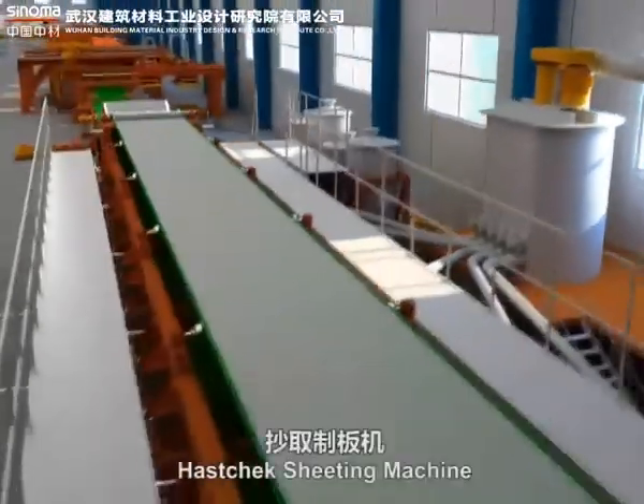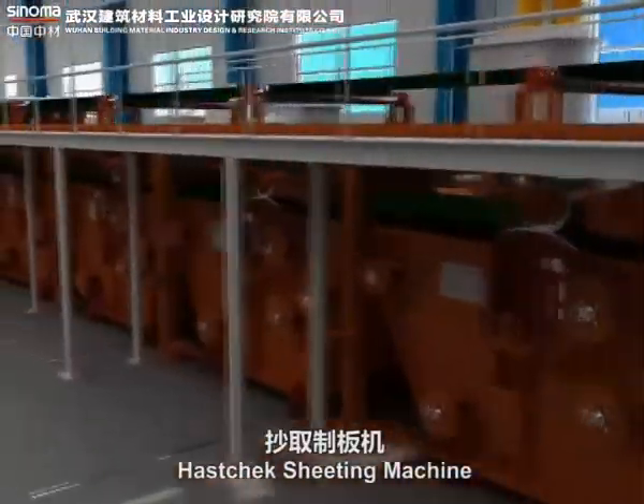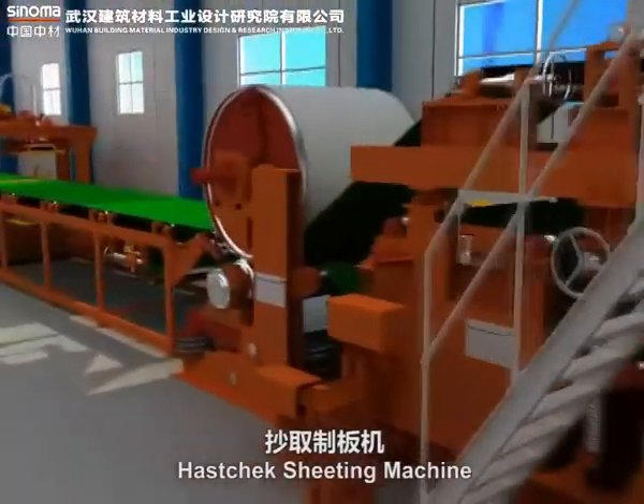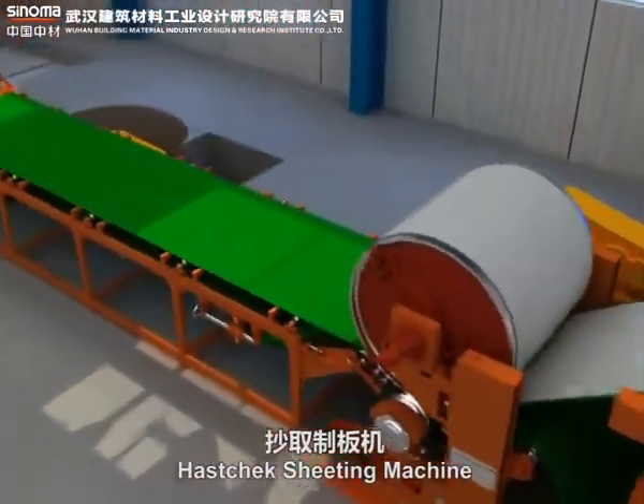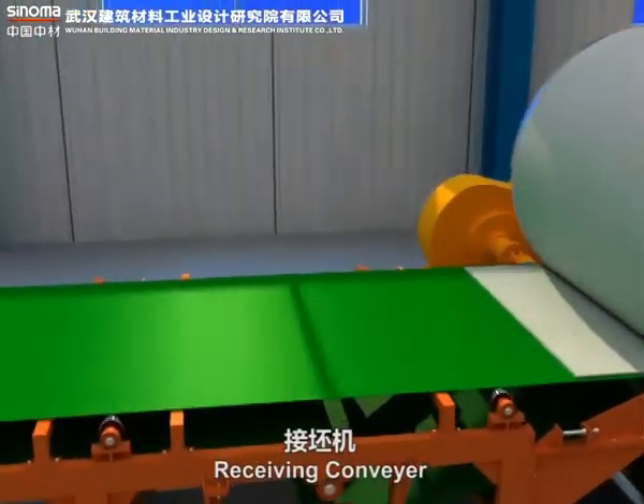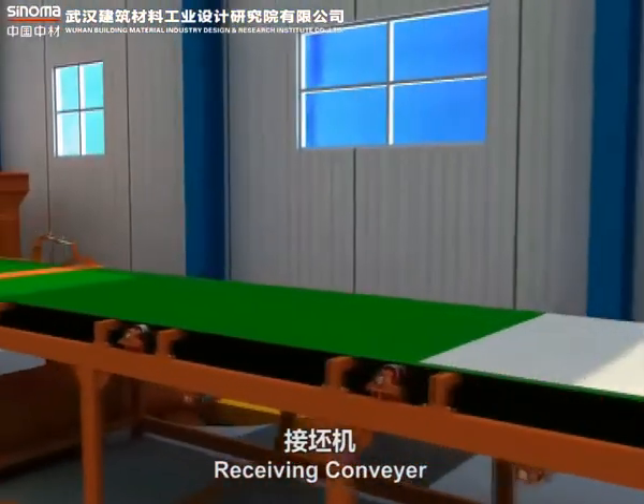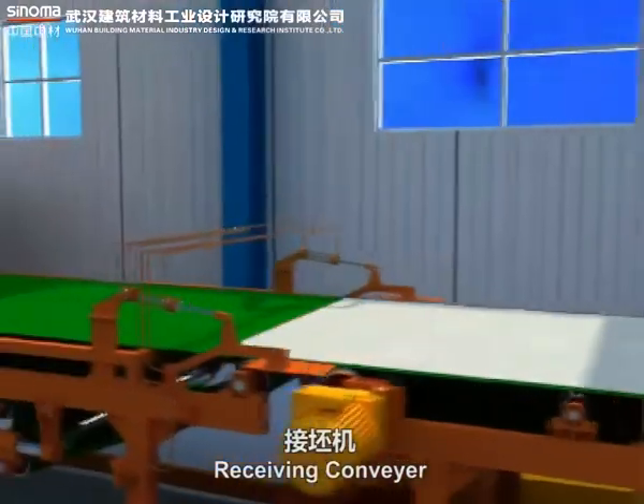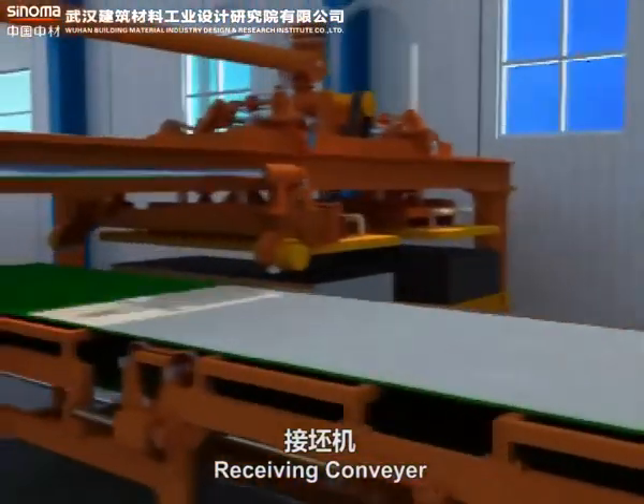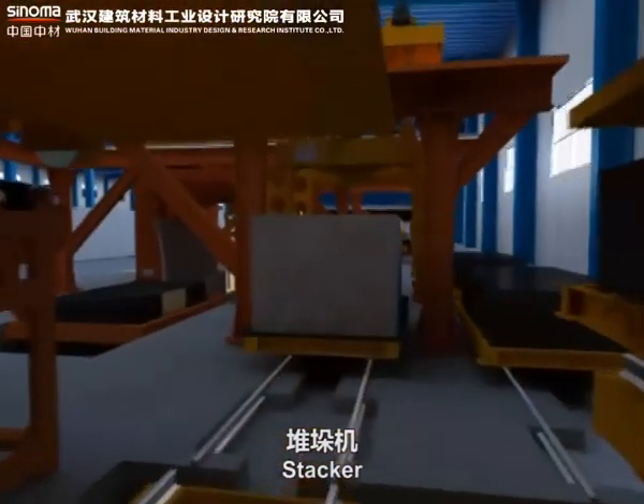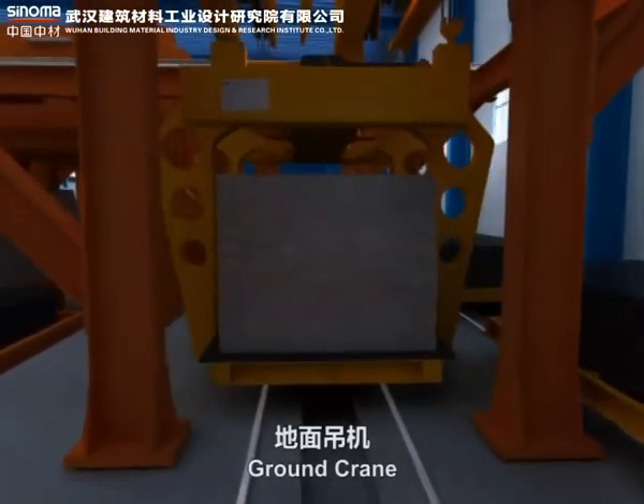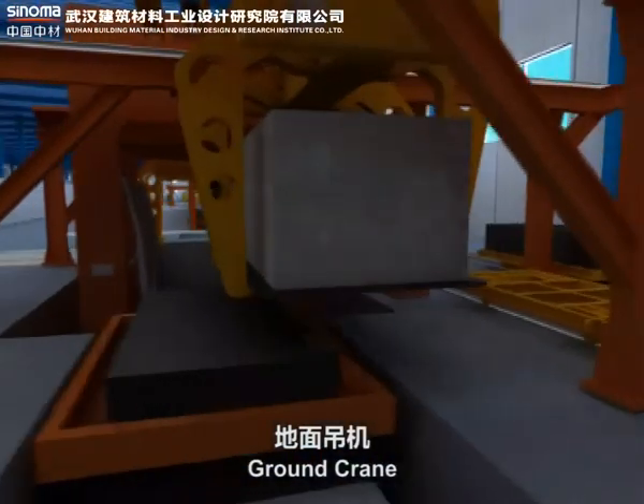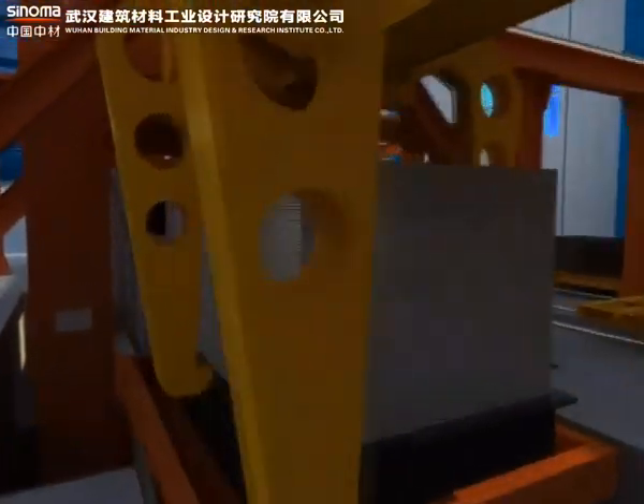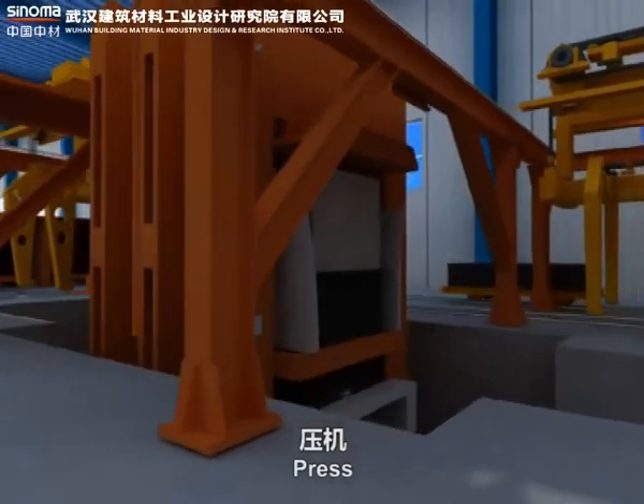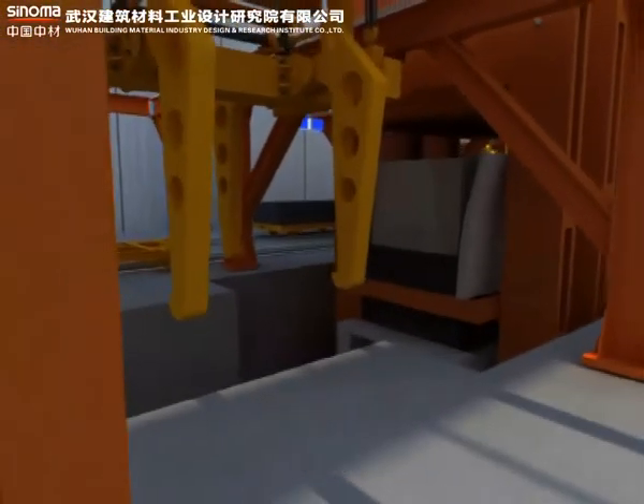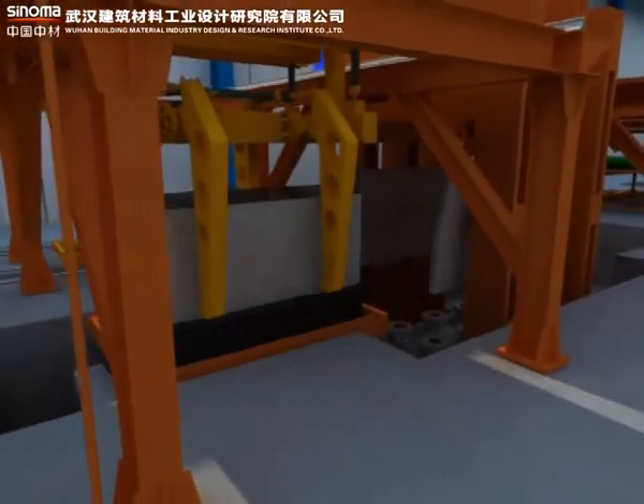For hatschek production line, the slurry has to get into the vats homogeneously. The paste-like material is fished out by sieve roller and then sent onto the running felt to get it formed, cut, and stacked. Wet boards, which need to be pressed, should be dragged to the ground crane automatically after being stacked. The ground crane then hangs the car full of wet boards up and sends it onto the press car, which drives a board into the press machine to get them pressurized.